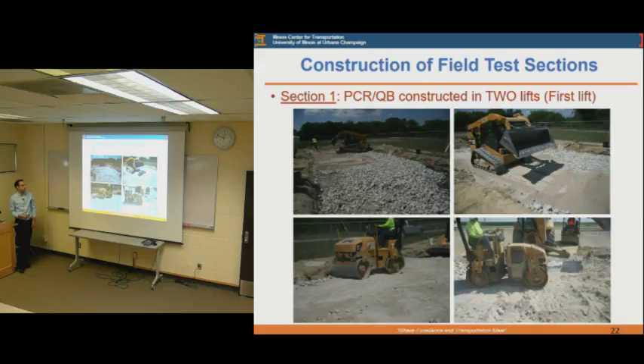So we first examined constructing the first lift of the 2-lift application. We had the large blocks placed, and then we had the Quarry byproduct, the 25% amount, placed on the top, spread with a skid steer, and then compacted. We were trying to simulate what we had in the lab, where a vibratory action makes the Quarry byproducts percolate into the voids of the large rocks. But in the field we ended up with a thin layer of Quarry byproducts compacted on the surface instead of percolating inside, which inhibited any further Quarry byproducts from going inside.